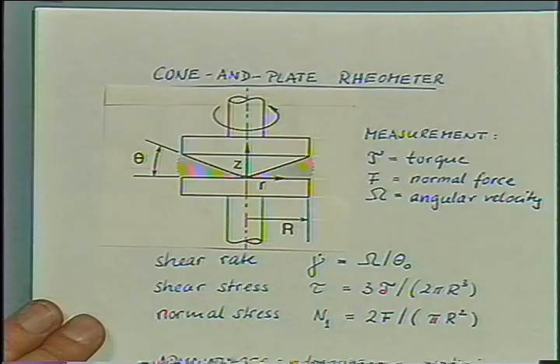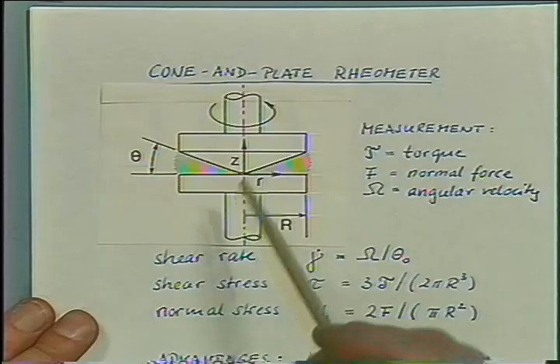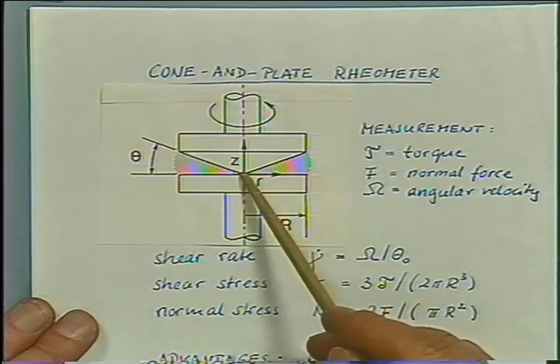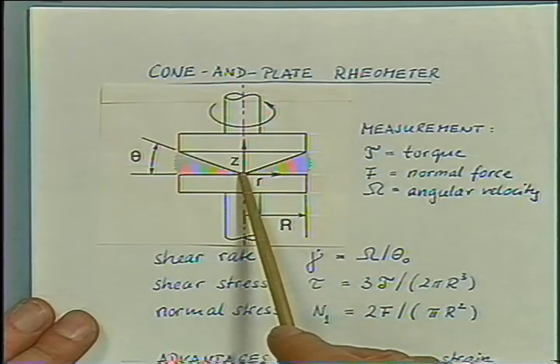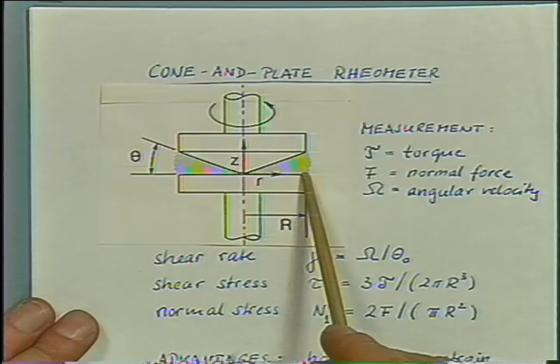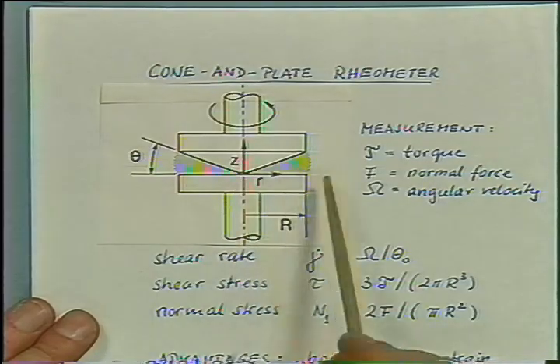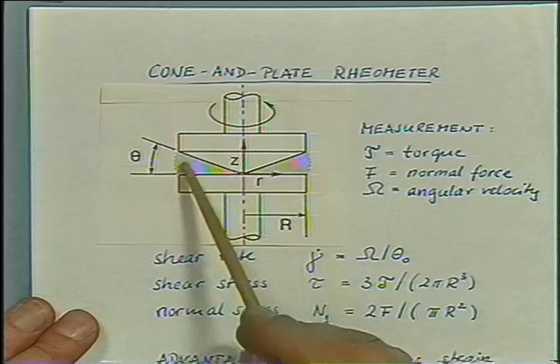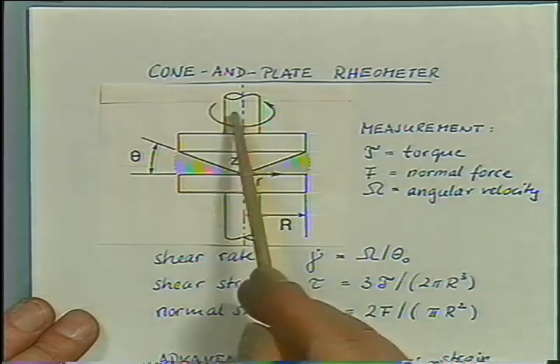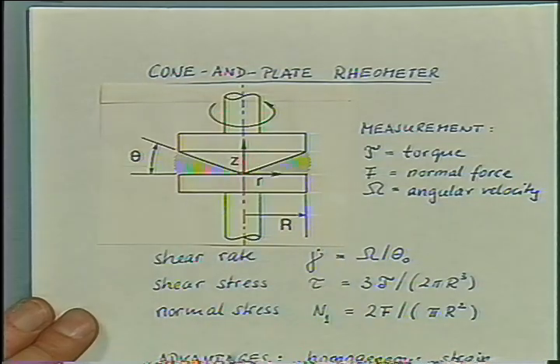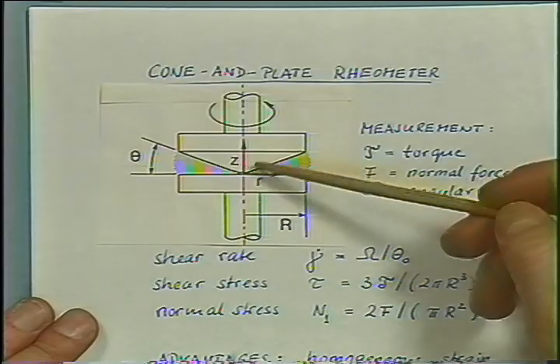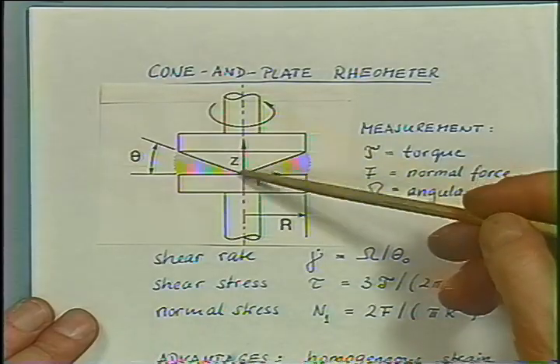The next geometry, and the geometry which we use extensively for molten polymers, is the cone and plate geometry. A cone with its tip sitting at the center of this disk is enclosing a sample. Now, one of the surfaces has to rotate. We would measure the angular velocity, we would measure the torque, and we also would measure the normal force, the force pushing those two halves apart.